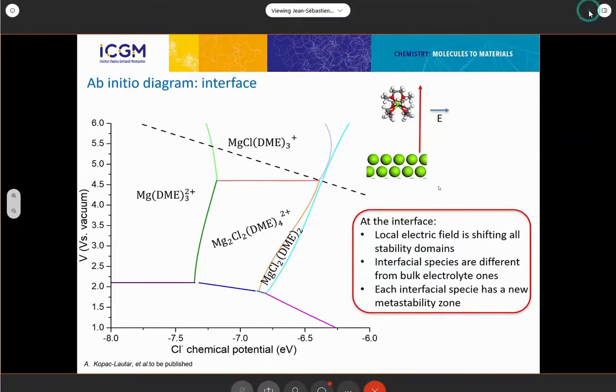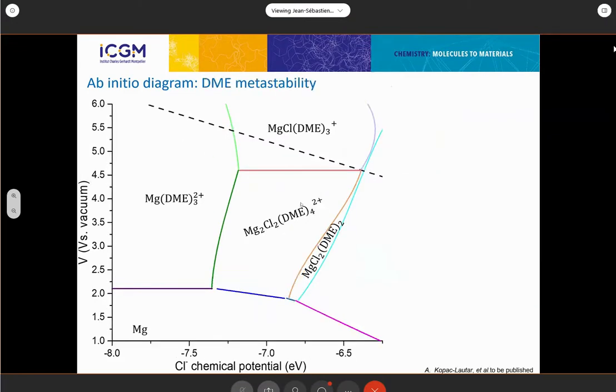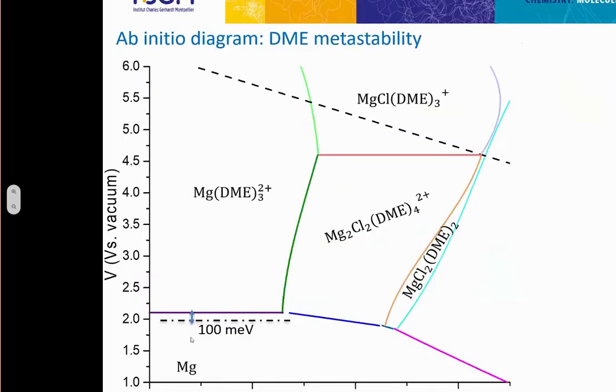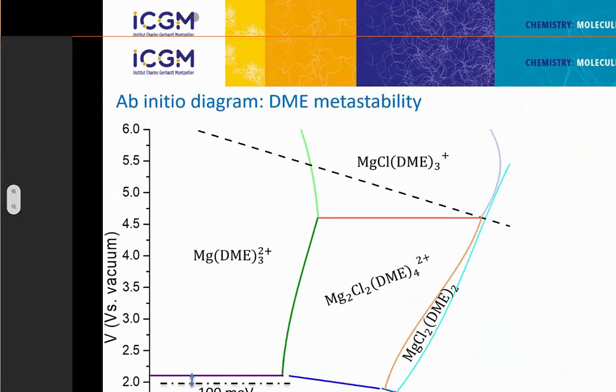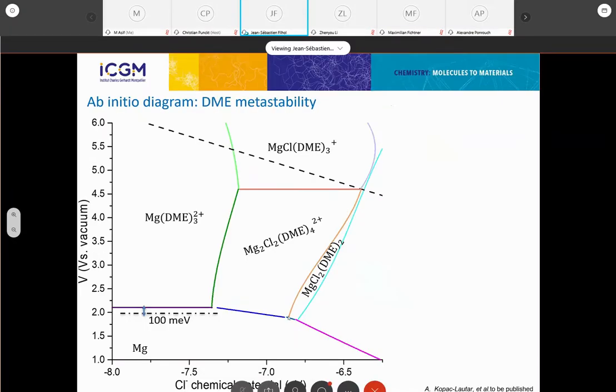And then once we have reached this, we can look at the stability of the species. Of course, with pure magnesium, we have observed a very low metastability of the DME. It starts to be reduced quite close to the limit of reduction of magnesium 2+. But if we use some chloride compounds, the metastability range is strongly increased. And the more we add, the more it is increased.